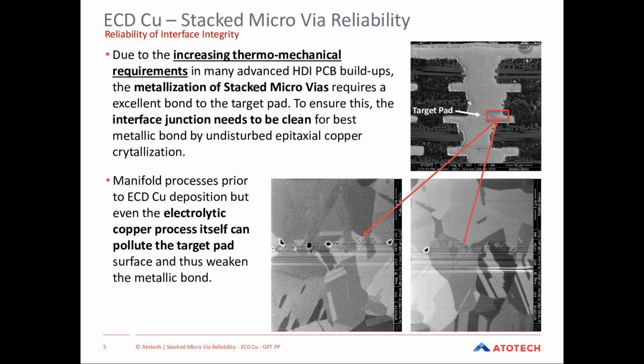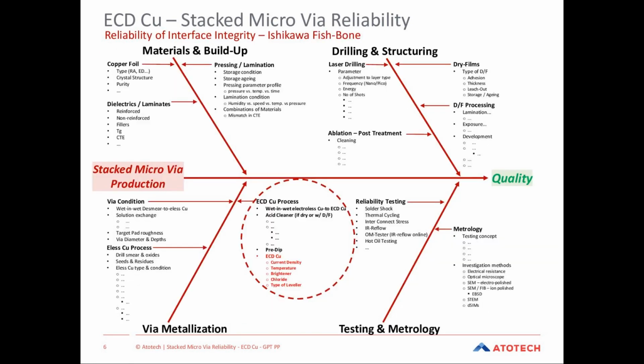And because the reasons can be so many, you see here a not exhaustive, complete fishbone diagram, but you see at least some of the main reasons, or the main process fields which have a direct impact to the quality of the target pad of micro vias. Apart from the materials and the build-up parameter itself and the drilling of the features in such build-ups, of course, the wet chemical processing of the build-ups is of major importance to avoid any interface contamination or interface weakness of the build of the stacked micro vias.